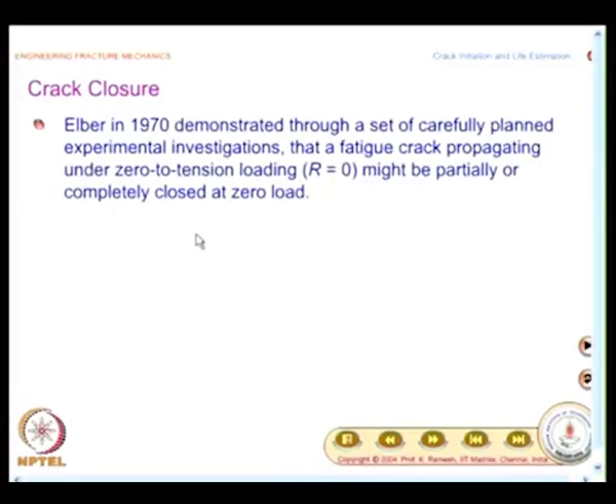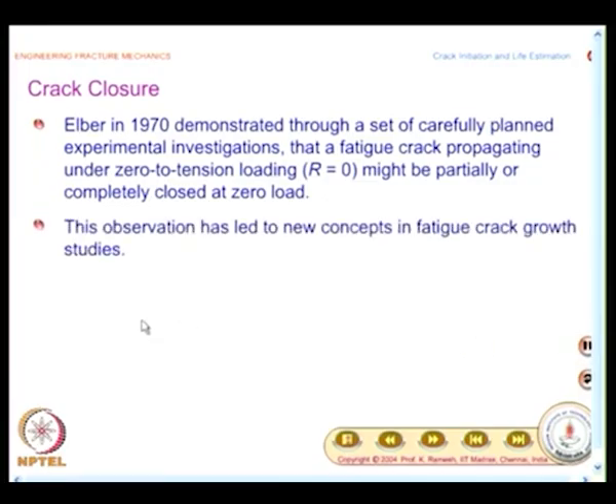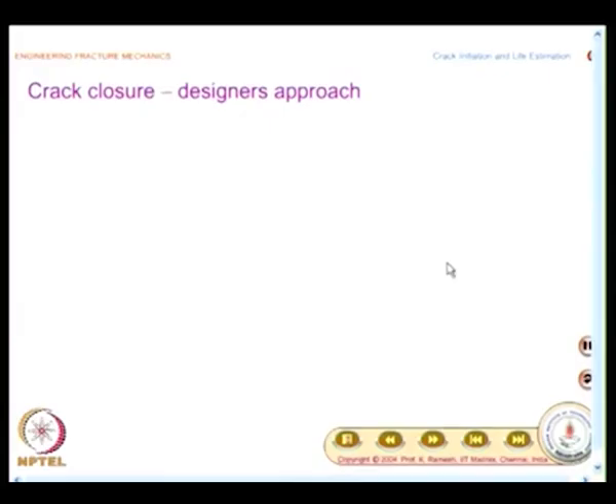So, this is what I had mentioned, which is summarized again. Elber in 1970 demonstrated through a set of carefully planned experimental investigations that a fatigue crack propagating under 0 to tension loading, that is R equal to 0, might be partially or completely closed at 0 load. And this observation has led to new concepts in fatigue crack growth studies, obviously after initial hesitation. People were not accepting his theory initially. Once they were convinced, people said how it could be modeled. The ultimate usage of this observation is how do you modify your crack growth calculation. There is a designer's approach. We will see that designer's approach first.